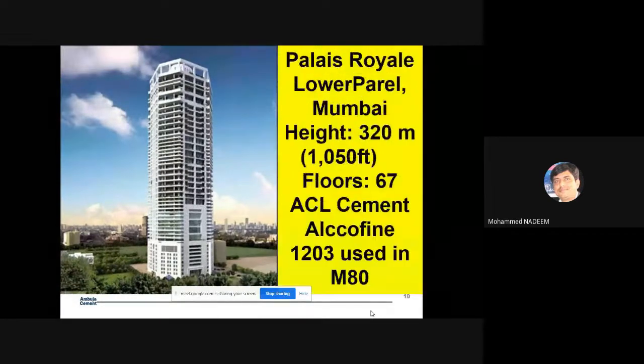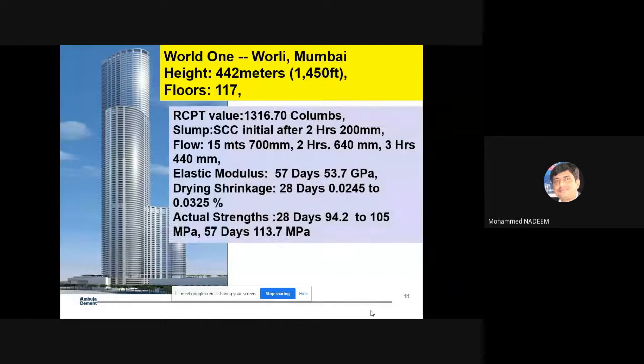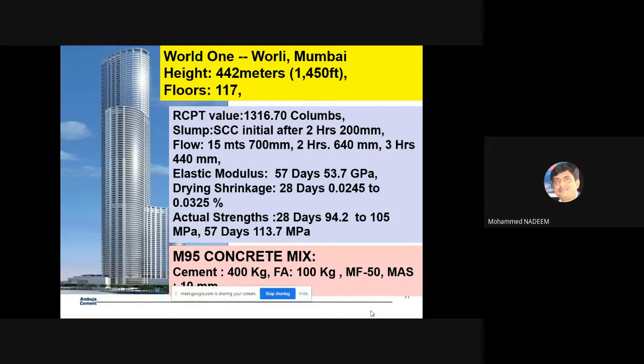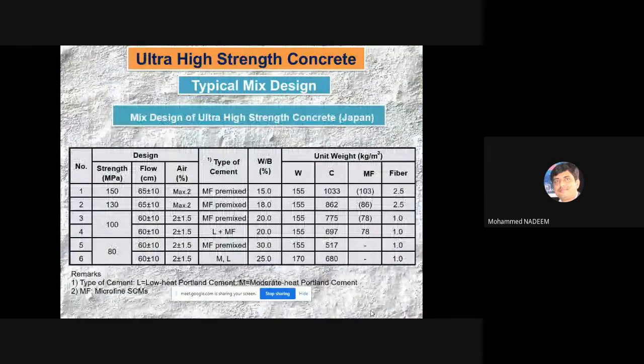In Mumbai also, in India, Palais Royale, a building already being constructed, uses M80 grade of concrete. World One, recently constructed, has an RCPT value of more than 1000, slump 200 mm, and this is how the requirement of elastic modulus and compressive strength is met. M95 grade of concrete, where they use OPC 400 kg, fly ash 100 kg, microfine materials 50 kg, and maximum aggregate size restricted to 10 mm. So that is possible, which people are using in modern or mega structures in India also.